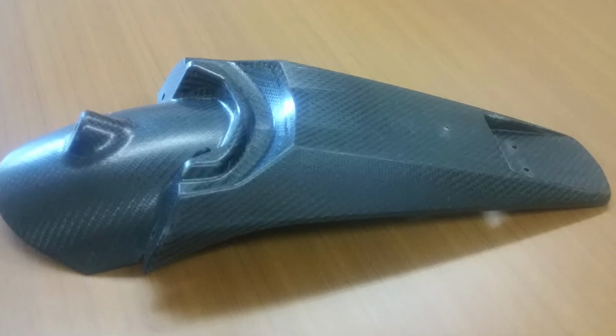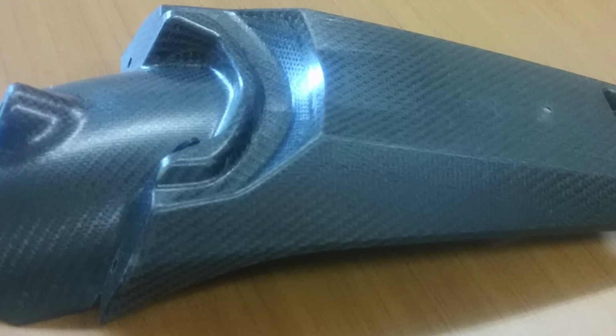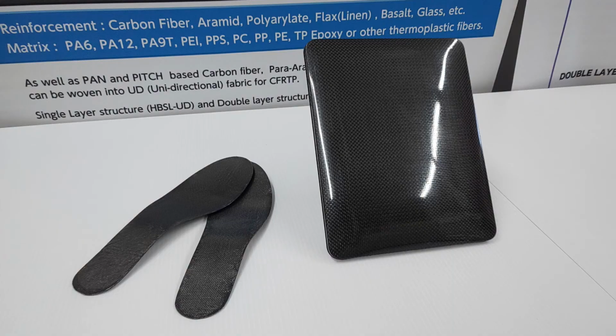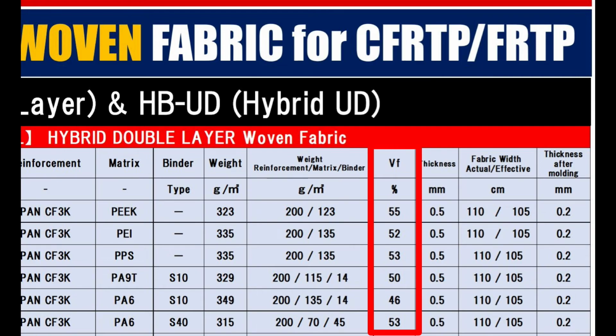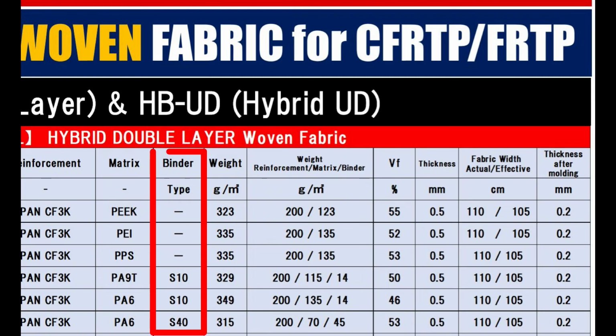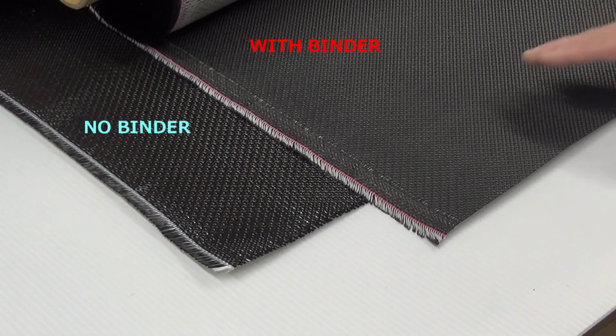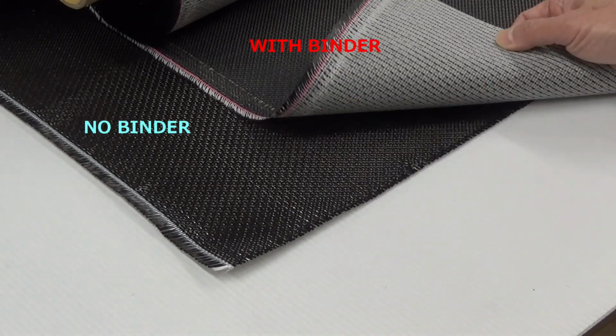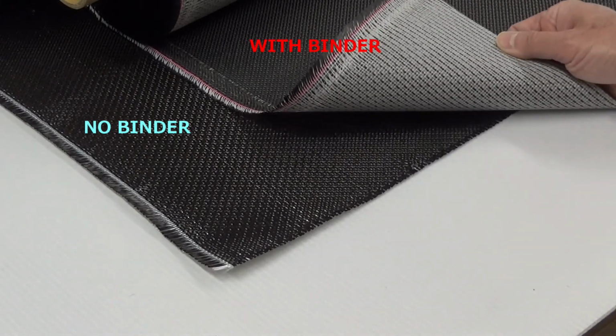For example, if you combine carbon fibre and polyamide 12, when polyamide 12 yarn is melted by heat, standard carbon fibre 3K 200 gram fabric remains as reinforcement in the composite. The VF, fibre volume, is around 50%, and this can be modified by the fabric design. For some combinations of certain matrix and carbon fibre, a special binder is coated on the fabric to avoid yarn fray when cutting and to improve impregnation into the carbon fibre.